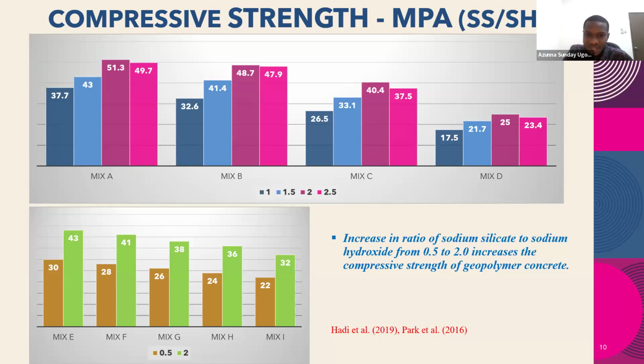So what it means is the sodium silicate is now too high, and the sodium hydroxide is very, very small. So what helps your concrete to attain a good strength is, one, the sodium hydroxide content in the geopolymer mix, and secondly, the calcium oxide and the silicon oxide in it. So if you reduce the content of the sodium hydroxide too much, you're not going to get a very high strength, regardless of the binder content that you used. Because the binder content is useless if the chemical composition is not broken down by the hydrates in the sodium hydroxide. So the reaction between the sodium hydroxide and the chemical composition of your binder is what fosters your strength.